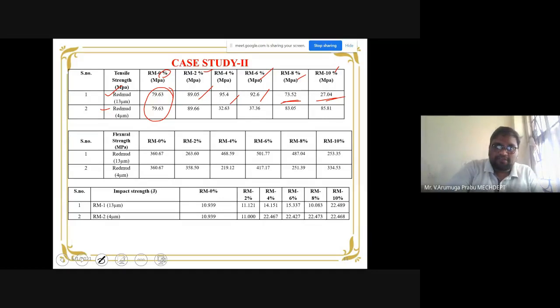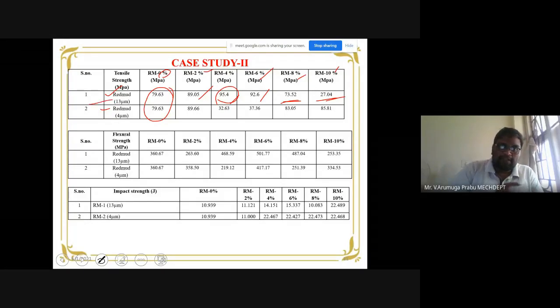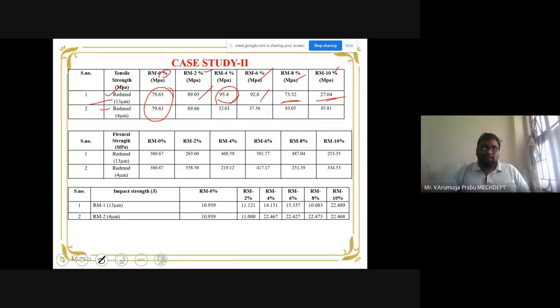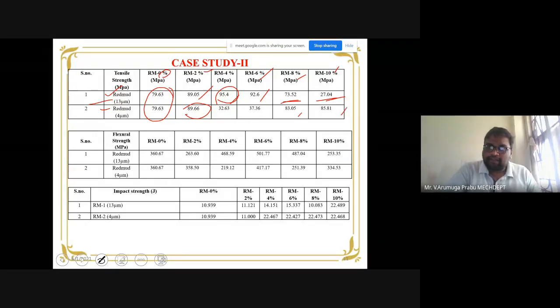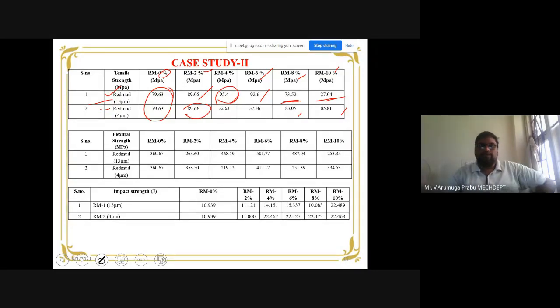Okay, so among the combinations, the 4 weight percentage possesses better results in the case of the red mud particle size 13. If you vary the particle size of the filler, that will also create a huge impact on your strength. Okay. That 4 micrometer particle size is going to give the highest strength of 89. That's for the 2% only. For all the remaining percentages it gets decreased, and it is slightly increased for 8 and 10. Okay. The reason may be due to the occupancy of your red mud dispersion.